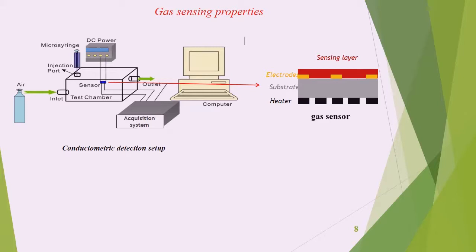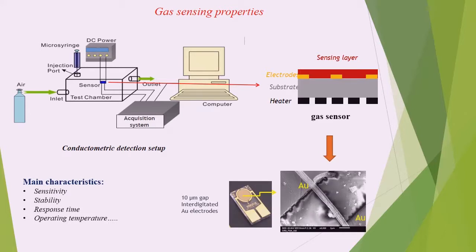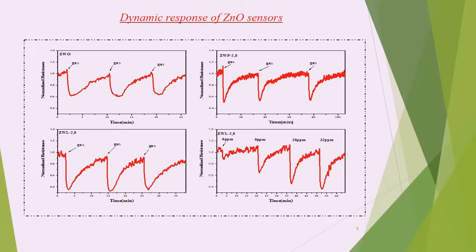The gas sensing measurement consists of a closed chamber with appropriate gas flow inlet and outlet. The target gas is injected into the test chamber at defined concentration using a syringe. During a typical gas sensing detection, a constant voltage is applied between electrodes of the sensing layer, and results are recorded with a computer system. A typical conductometric gas sensor consists of an active sensing layer in which conductivity changes upon exposure to target gases. The adsorption of gas molecules on the sensing layer induces a redox reaction which depends on the reductive or oxidative nature of the target gases.